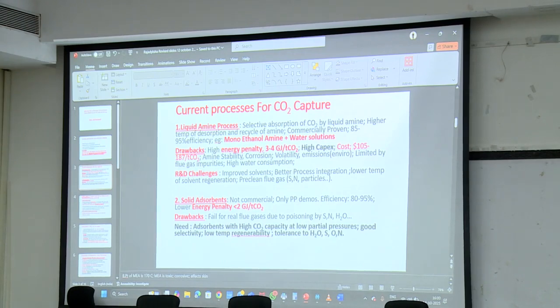In a sugar factory, the carbon dioxide is very pure, 99%. But a coal-fired power plant flue gas contains so much sulfur, nitrogen, oxygen and particles that the solvent should be able to handle it. Right now it is not. Next is the solid adsorbent, which can absorb the carbon dioxide and then desorb it, using pressure or temperature desorption. But these are not commercial, only pilot plant demos. The efficiency is good and they have a lower energy penalty, only 2 gigajoules per ton of carbon dioxide, whereas it is double in the case of liquid amine.